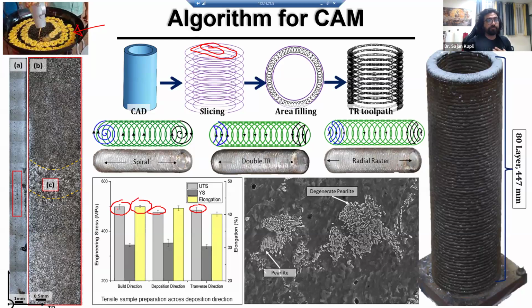And this was a very interesting result, because typically we think 3D printed parts are not strong in the build direction, but not really. If you plan the path accordingly, you see. And not only that, the parts deposited by this were quite homogeneous in the microstructure. We were struggling to find heat affected zones, which are a very common zone in welded parts. It was very difficult. You can see the sample, a very tall wall, and then we took a sample out of that in this region, and there is some coarser microstructure in this zone, but not very clearly visible.